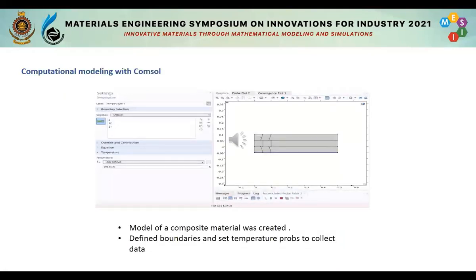When it comes to computational modeling with COMSOL, first of all, we developed a model for a specific geometry in which we can change the percentage of cotton and LDPE as desired. So here in this figure, you could see that there are three layers, and in these three layers, we could change the percentage of cotton and LDPE. While changing the percentages, we kept the bottom surface temperature at room temperature and the top surface temperature at a higher temperature like 373 Kelvin.